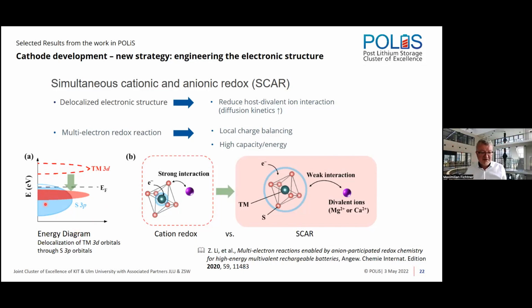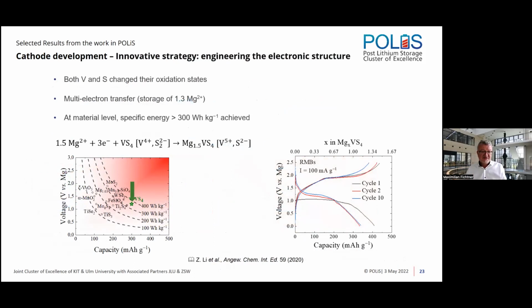And this is an example of one of our model compounds, where we had actually discovered this. This is a case where the transition metal 3d electron band interacts with the sulfur 3p band, so that you get a delocalization of these orbitals, and you get a better access of the electrons by these means. This was discovered by Chen-Yu Li here at the INT, and he called this principle SCAR, simultaneous cationic and anionic redox. The first compound where this was studied was the vanadium tetrasulfide. This is a natural mineral called patronite.